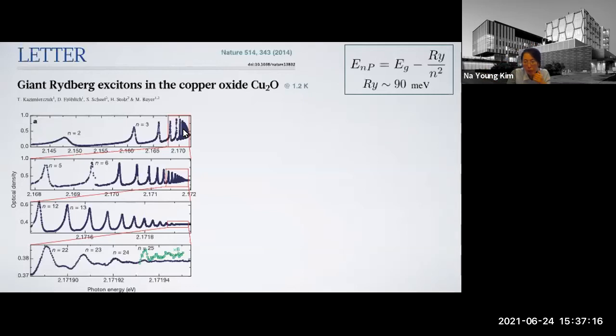Particularly because of the dielectric constant in the presence of the large crystal host, the dielectric constant is normalized, and the effective mass is renormalized as well. In this case, the Rydberg constant, the binding energy, is 90 milli-electron volts. In the hydrogen case you have 13 eV, but in excitons in semiconductors, it's almost 100 times smaller, at 90 milli-electron volts.